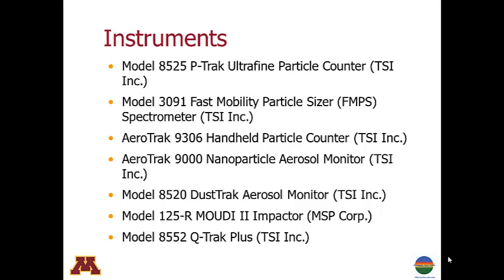A nanoparticle aerosol monitor measured surface area concentrations of particles ranging from about 10 nanometers up to about 1,000 nanometers or 1 micrometer in diameter. We used a DustTrak photometer with a PM2.5 inlet to measure mass concentrations of particles ranging from about 100 nanometers or 0.1 micrometer up to 2.5 micrometers in diameter. A MOUDI cascade impactor was used to sample particles onto substrates that were subsequently observed in a scanning electron microscope, or SEM, to determine their morphology. As I mentioned previously, the Q-track was used to measure temperature and relative humidity inside the granulator enclosure.